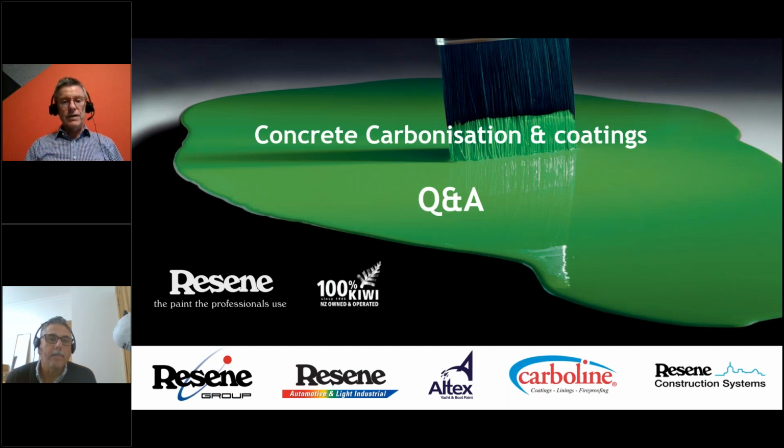So hopefully, if we're being asked those questions at sites, we're having these kinds of chats and giving the right information around the real potential for creating a problem. And where you were going with the Aquapel in lieu of graffiti shield, graffiti shield is a film forming clear coating, which is a non-sacrificial coating is the term. So it's a clear coating that you wipe graffiti off. There are other anti-graffiti coatings out there that are sacrificial, wax-like coatings that penetrate and essentially disappear on the surface. And when you take the graffiti off those products, you're taking the sacrificial anti-graffiti coating away at the same time, and you need to reinstate that. We choose not to have those in our range.